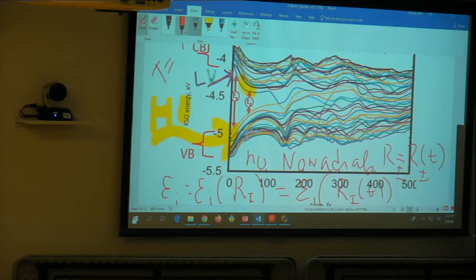Typically, one would expect that thermal energy is kT, or room temperature kT is like 0.03. However, here we have it like it changes by 1 eV. So just keep thinking of this paradox and be prepared. But the first thing you ask for sure. Okay? So the critics may not like this numerical observation. Just try to make it comfortable.